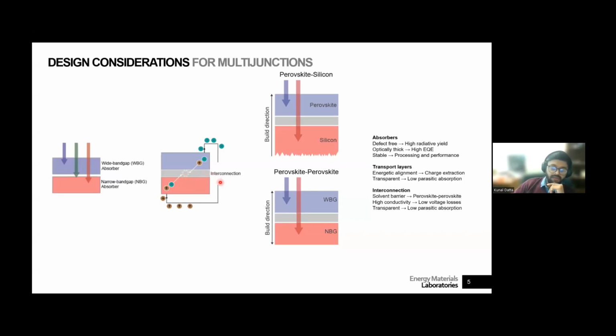And in terms of how to construct such a device, for instance, for a perovskite-silicon tandem, there's only one way to build it up, and that's that you start from the silicon cell and then you build up the perovskite, and that's primarily to do with processing considerations. The temperature and what kind of harsh processes you use for a silicon cell, you cannot do when you're doing it on top of the perovskite. So you need to do the perovskite at the end.